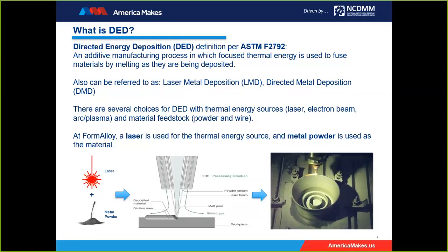Now, I want to talk a little bit about the diagram on the bottom that shows in more detail what is happening in the process. You'll see there's a coaxial nozzle. Out of the outer nozzle is where the powder comes, and that forms a powder cone. In the center of that coaxial nozzle is the laser beam. That creates a melt pool, and the powder cone is formed into that melt pool, and then parts are built up layer by layer. You can see on the video on the right, that's an in-process part being built, and you can see there's a melt pool that's the brightest part, and you can slightly see the powder cone above that that's being fused into that melt pool as it's filled. Now, with directed energy deposition, you're getting a full metallurgical bond upon deposition.